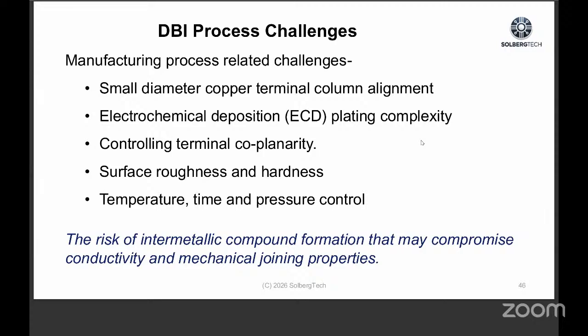Process challenges ahead. We're going to have smaller diameter copper terminals, and the challenge is column alignment. Deposition of the plating is another challenge. Controlling terminal coplanarity, surface roughness and hardness, temperature, time, and pressure control. The risk of intermetallic compound formation may compromise conductivity and mechanical joining. So the cleaning process, I think it's a very aggressive plasma cleaning process to make sure that there's absolutely no oxidation on the surface of the copper, and of course no particles can be tolerated. Next slide.